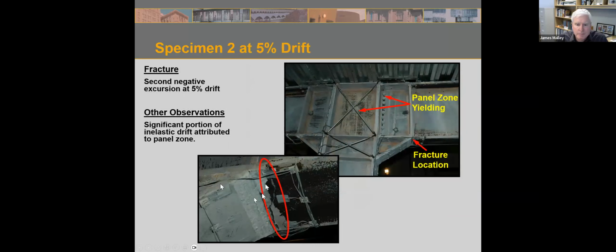Eventually, at the end of the second cycle and the 5% drift, we did get a fracture adjacent to where the haunch came into the beam flange. And this is sort of, I guess you'd call it low cycle fatigue, because there's so much demand back and forth, shear strain being sucked up in every one of those cycles, that eventually something has to break, kind of like a paper clip, right? If you keep twisting it enough times, it's going to break.